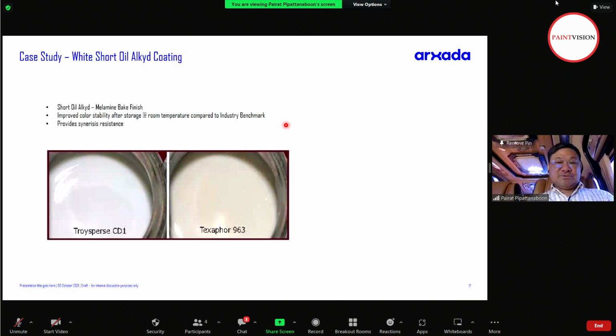CD1 also helps in terms of syneresis, controlling the oil floating from your formulation. This is a short oil alkyd melamine bake finish after storage at room temperature, and then you check for oil floating on the surface. With CD1, there is nothing there.